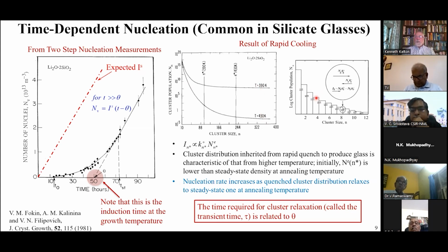So that takes time. So initially, the nucleation rate would be the critical size at the lower temperature, if we're measuring it at 390, multiplied by the equilibrium distribution. The equilibrium distribution should be here. But actually, when you start, it's way down here. So you have orders of magnitude lower nucleation rate. As you let it proceed, this distribution will relax to the distribution at the temperature at which you're doing the nucleation measurement. So it's the fact you're quenching the liquid quickly to form the glass that gives rise to this effect.